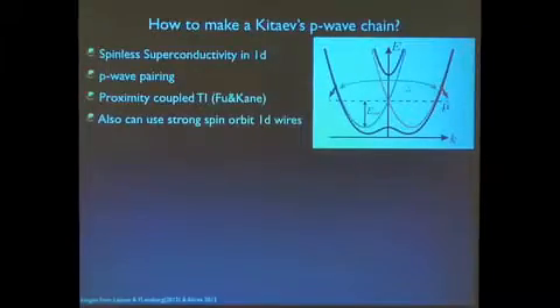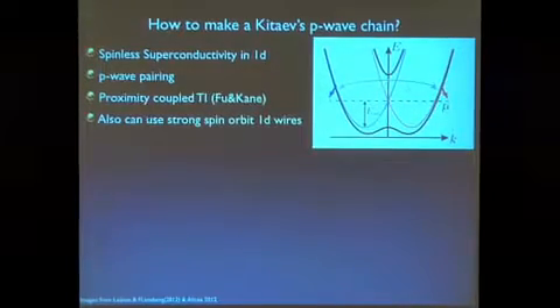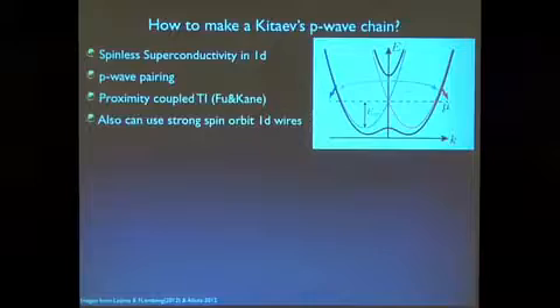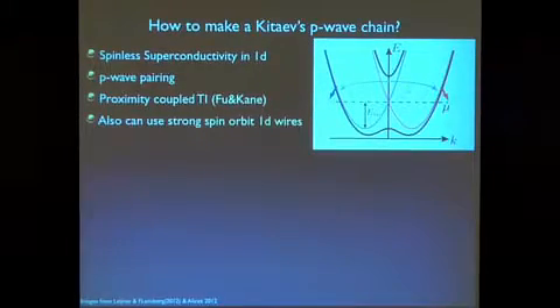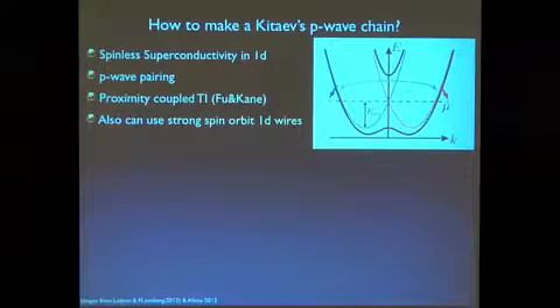So this subject is all the rage because it's subject to quite a bit of work, even here at Harvard, where people are trying to come up with ways in which you can generate such a chain, the Kitaev chain. It's called P-wave because the superconductivity is not with pairs on the same site, it's pairs on the nearest neighbor site. Now, how do you make spinless paired electrons?